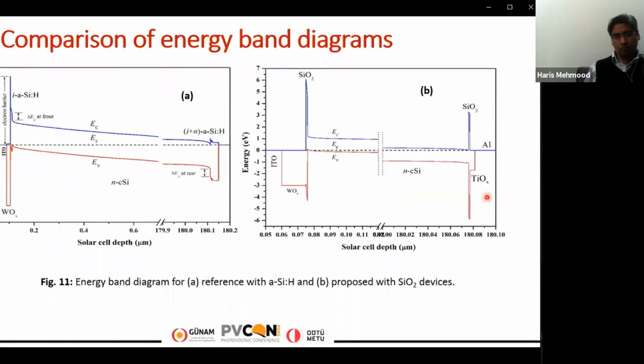So the comparison of the energy band diagram with the a-Si:H structure and our proposed structure shows that with the intrinsic amorphous silicon passivation layer, an electron barrier height of around 3 electron volts has been observed. Whereas if we incorporate a silicon dioxide layer as a passivation layer, then the electron barrier height would be further improved to around 6 electron volt.